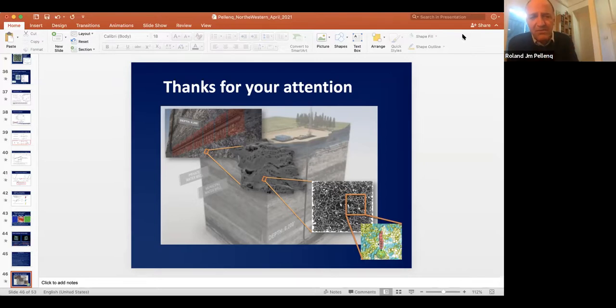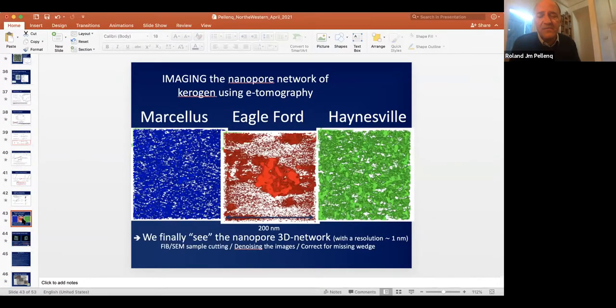It also depends on the type of chemistry. Remember that I was showing, maybe I can go back a few slides, this one here. You see, these are different Kerogens. The Marcellus is very, very mature. It's made only of nanopores, up to 2 nanometers. So in that one, there's no Darcy. The Eagle Ford is very immature, so it is a young Kerogen. Maybe that's the Marcellus in 300 million years; Eagle Ford is maybe 50 or 100 million years. So in those, yes, you have big pores. But the thing also is that if you look at the texture, the big pores are not connected. So the transport will have to happen through the nanopores. So in that sense, Mr. Darcy, you are still mistaken.